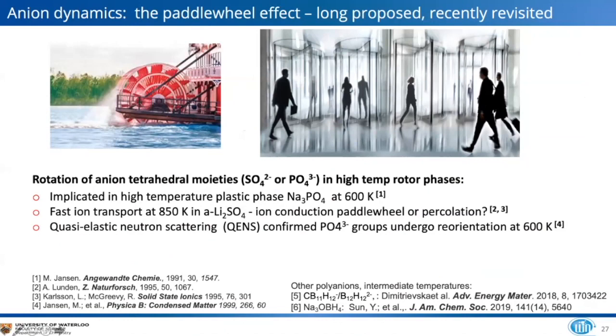And it relates to this concept, which was developed actually long ago and has been recently revisited, which is sometimes called the paddle wheel effect. And we actually prefer to make an analog more to a revolving door, in which the motion of the framework is actually aiding the mobility of the cations, just as one passes through a revolving door. So just to put things in context, the rotation of these anion tetrahedral moieties and polyanion materials in, for example, sulfates or phosphates was implicated in high temperature rotor phases.